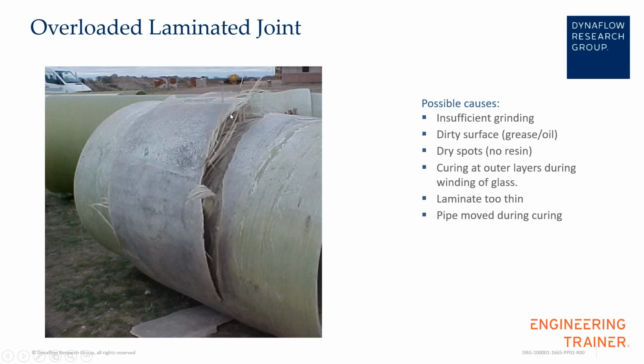So when the outer layers of the joint are curing while you're still winding more glass material, while you're still manufacturing the joint at site, then the cured resin is not bonding well with the glass, and then you have an issue. And of course that issue especially plays in warmer environments like the Middle East. Then of course the curing is faster and you can get this problem. To counteract the curing, in cases of high temperature, you can add delayer to the resin. That just delays the hardening process.